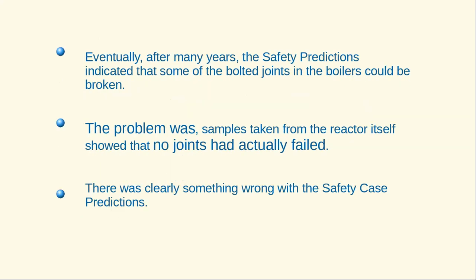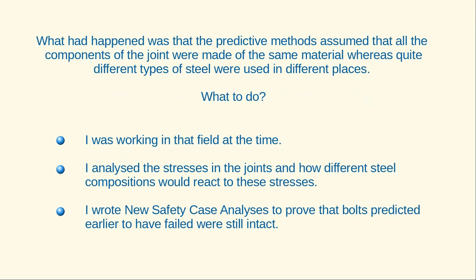Eventually, after many years, the safety predictions indicated that some of the bolted joints in the boilers could be broken. The problem was samples taken from the reactor itself showed that no joints had actually failed. There was clearly something wrong with the safety case predictions. What had happened was that the predictive methods assumed that all the components of the joint were made of the same material, whereas quite different types of steel were used in different places. What to do?